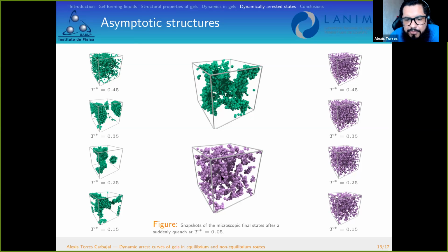Now, for the lowest temperature that we studied, we can see that in the case of the Lennard-Jones with the long-range repulsions, there is a formation of some kind of elongated cluster that spans the whole volume of the box. And this is the signature that we are looking for of an arrested state. So we can establish that at this temperature, which is much lower than in the case of the Lennard-Jones, we already see an arrested state.